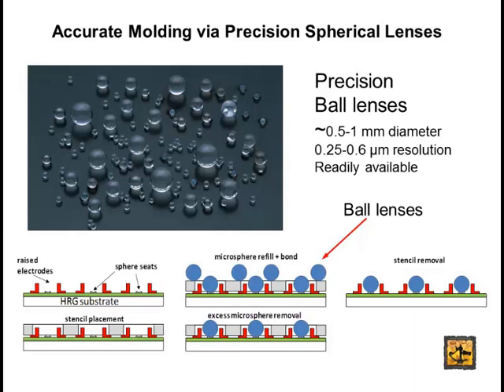And if you pay a little bit more money, you can get it within a quarter of a wavelength, about 0.25 microns. So these are readily available. The idea was to replace the other balls with these lenses so you get this precision surface. In this manner, you can take a substrate with all the features that you may want to have on it, like maybe electrodes to make a driver shell, for example, and posts for specific locations where you place the shells. Then you put a stencil on top, spread these ball lenses on top, shave off the excess ball lenses, and remove your stencil, and you end up with the molds placed at the right locations.